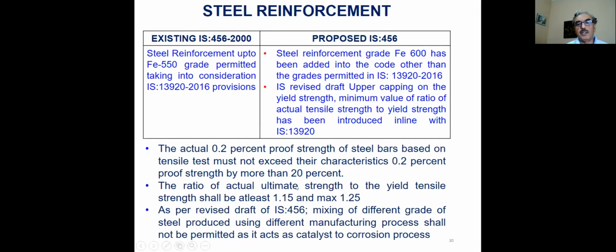Similarly, the ratio of ultimate to yield shall be at least 1.15 and not more than 1.25.